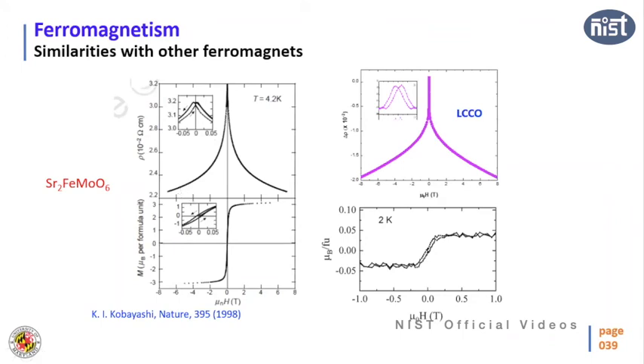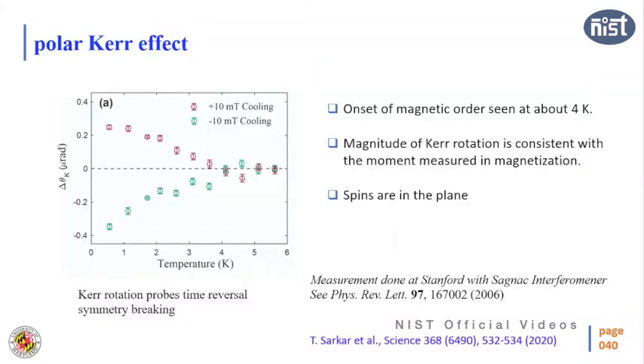Now we wanted to confirm it further because there is always a chance of mistake, because ferromagnetism is quite difficult to prove sometimes. Then we did another very powerful measurement, which is Kerr rotation. This measurement was done at Stanford in collaboration with Kapitulnik. Again, this measurement also shows there is a ferromagnetism. What it means is that in Kerr rotation, this angle, the Kerr angle as we say, basically measures the magnetization. It's very similar to magnetic susceptibility.